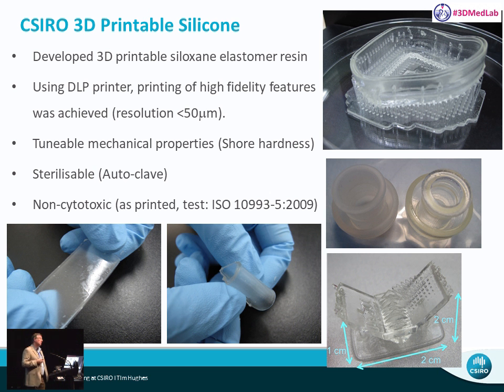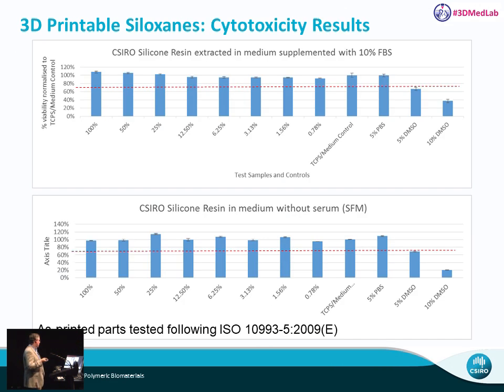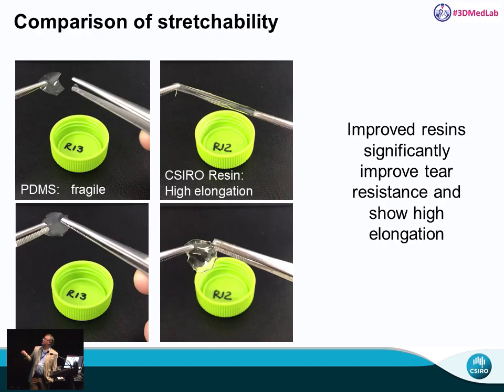And after a lot of blood, sweat and tears, we were finally able to make materials with really close replication to the original designs. So these are siloxane-based resins. They're printed on commercial DLP printers without modification. We get really small features, so this is around 2 centimetres by 1 centimetre. So the features here are less than 50 microns.